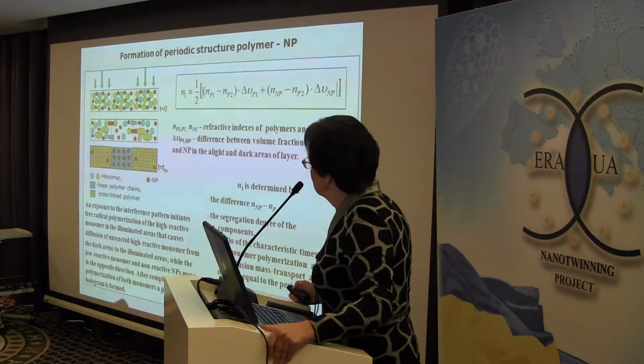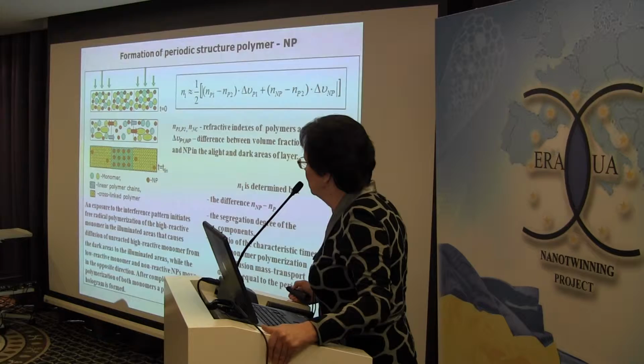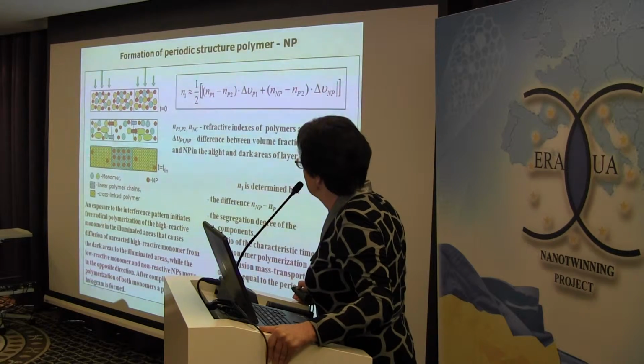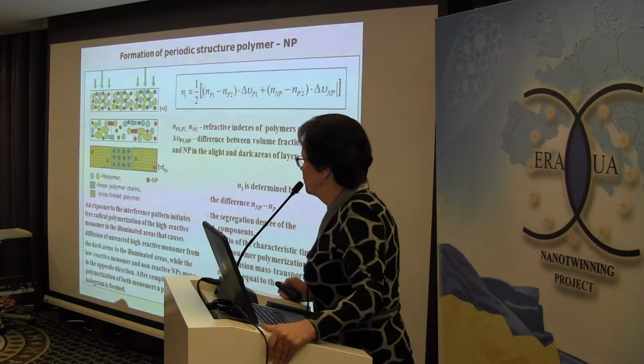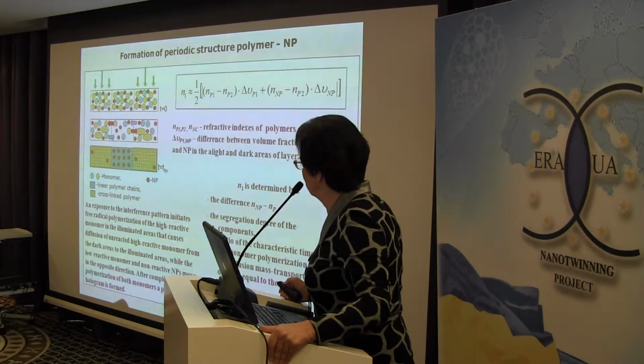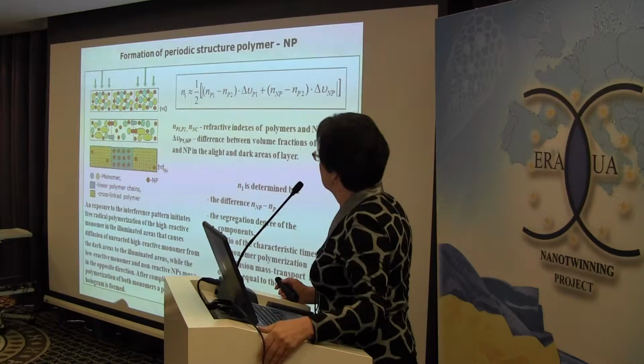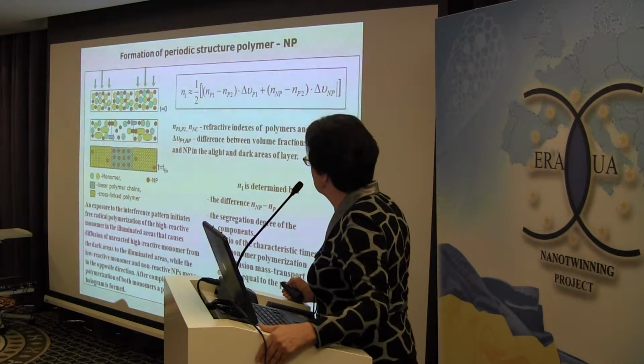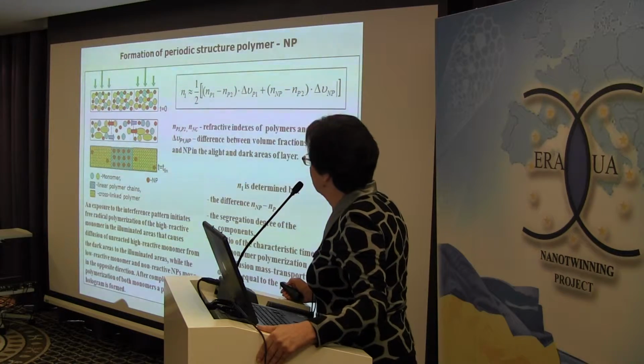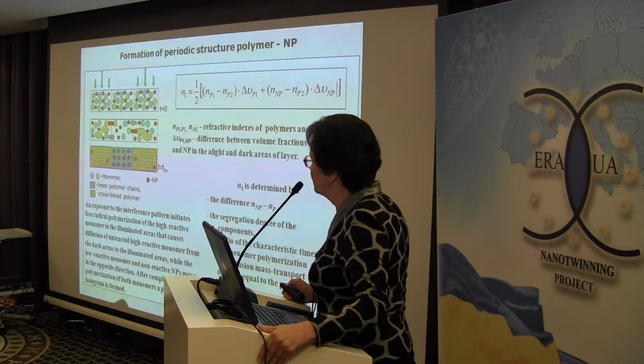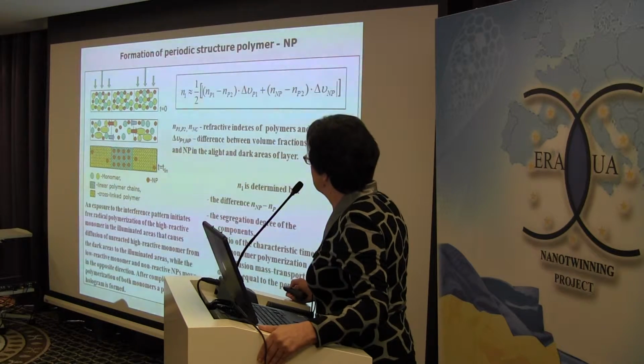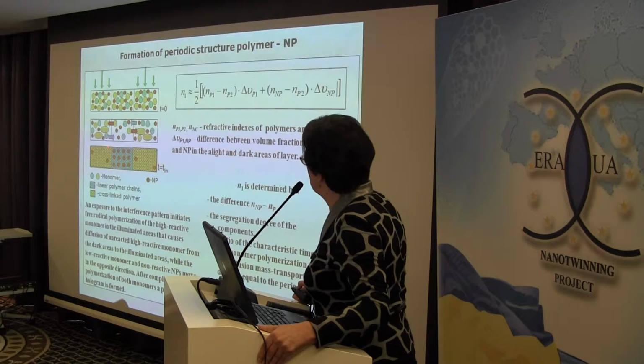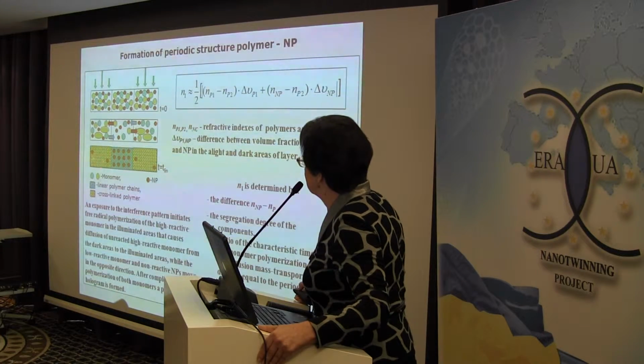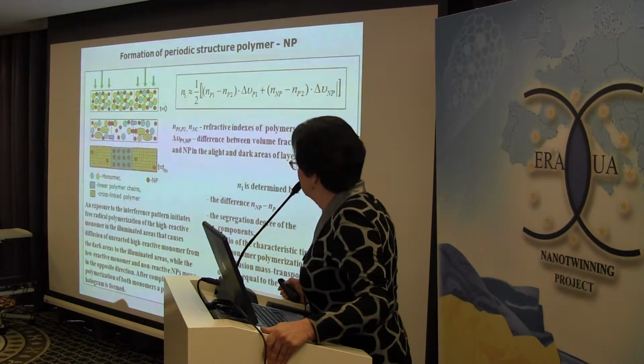At the same time, the low reactive monomer and nanoparticles move in the opposite direction. After the full polymerization of both monomers, the permanent structure is formed. The amplitude of refractive index modulation of this structure is determined by the difference between the refractive indices of polymer-rich and nanoparticle-rich areas.